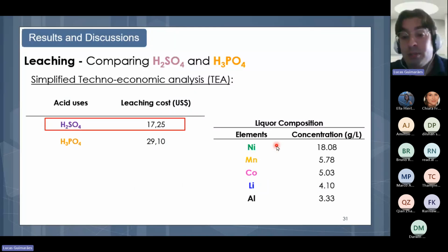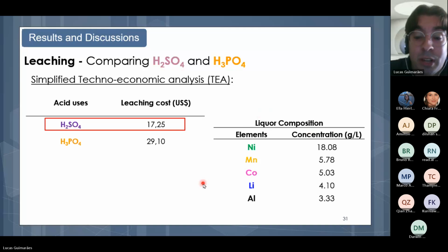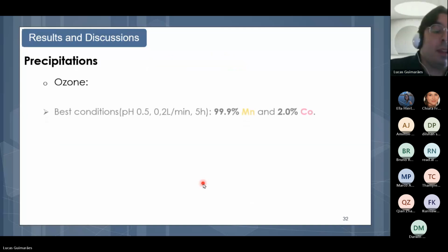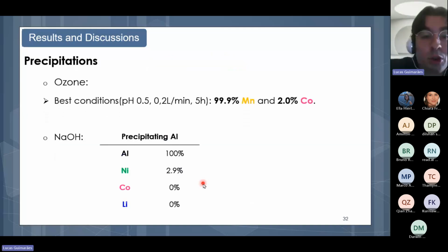The synthetic solution that was created for the next steps has the same composition as the leaching liquor using the best conditions of sulfuric acid leaching. The results for precipitation with ozone at the best conditions: it was possible to recover 99.9% of manganese, with the lowest amount of co-precipitation of cobalt, which was 2%.